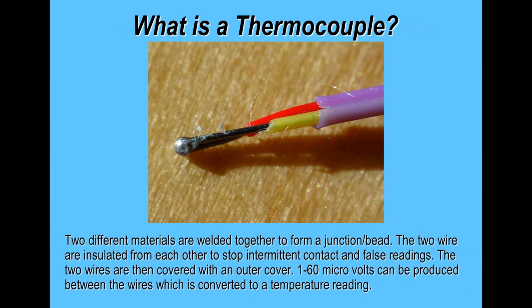Which brings me on to thermocouples. Now a thermocouple basically measures very small changes in electrical value as the thermocouple bead, which is right on the tip of the two leads you see here, changes temperature. And your profiling system monitors those changes and equates those to a temperature change. Now there are lots of different thermocouples available, but the key thing with a thermocouple is making sure that you're actually using it the correct way.